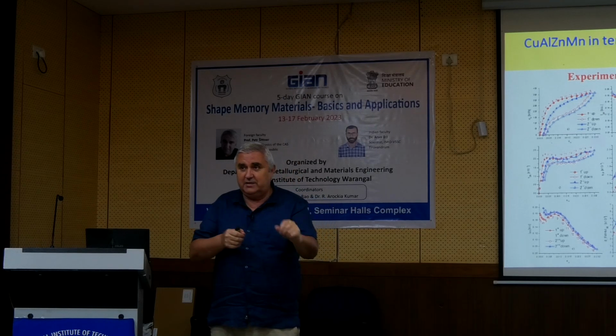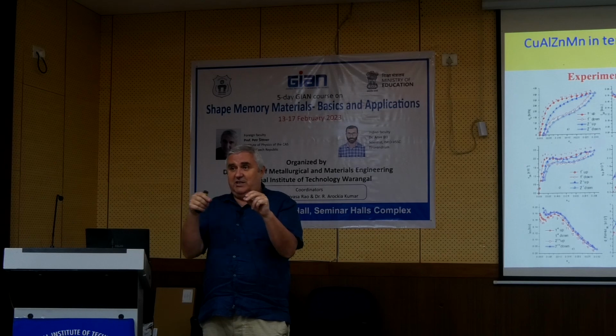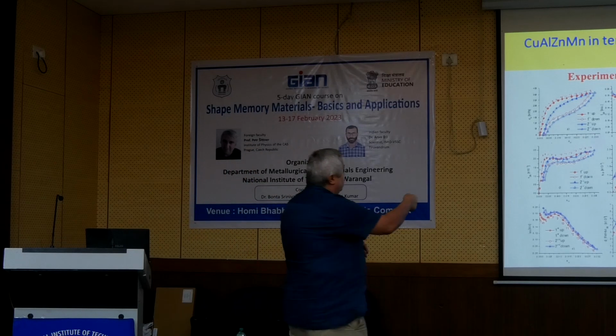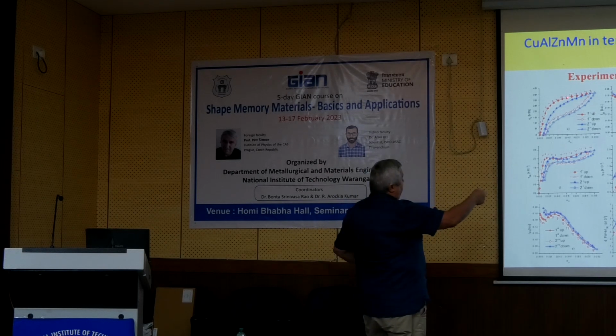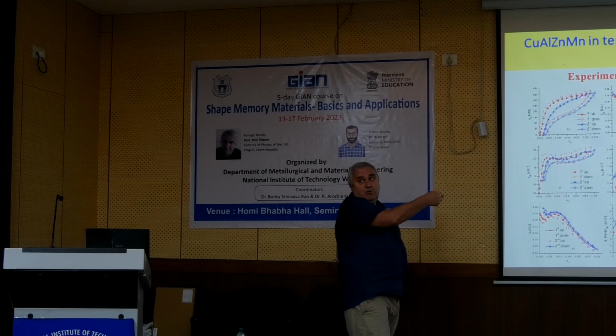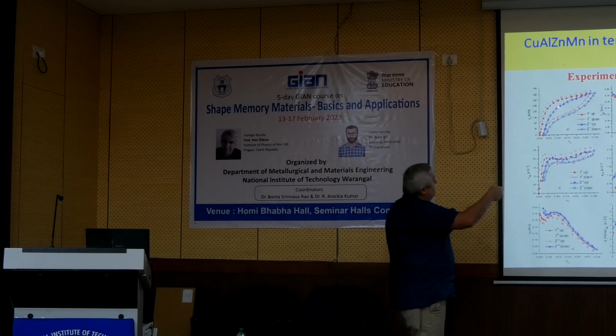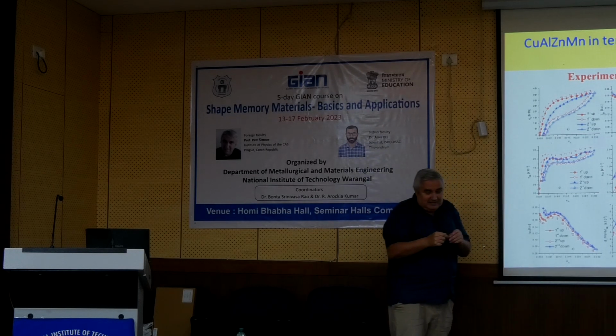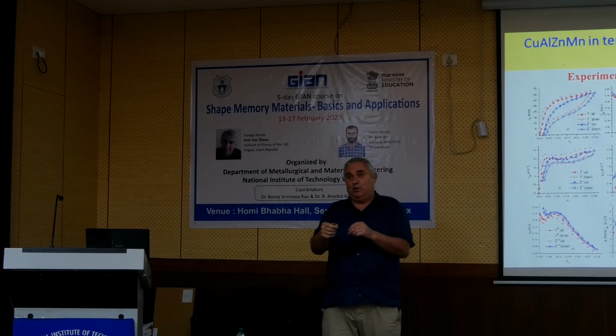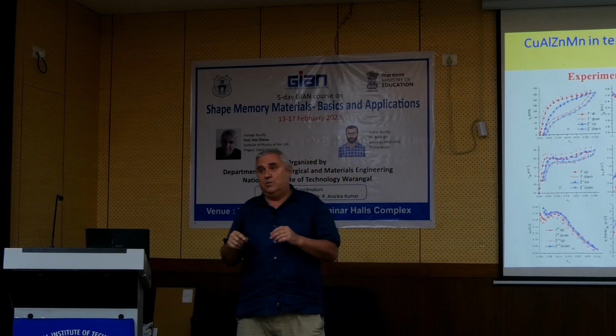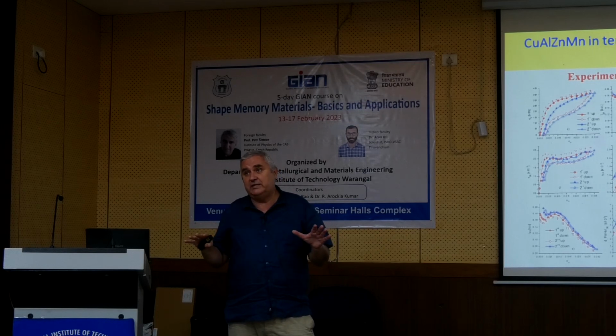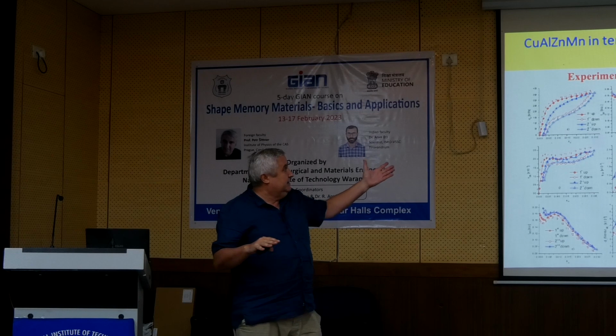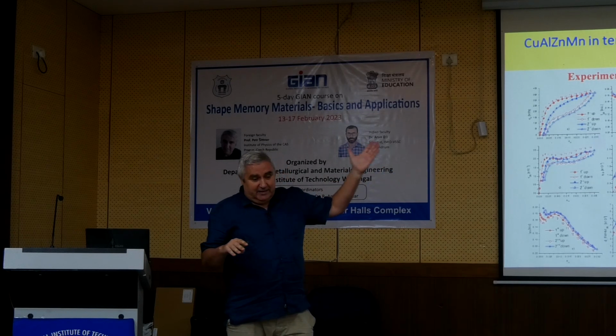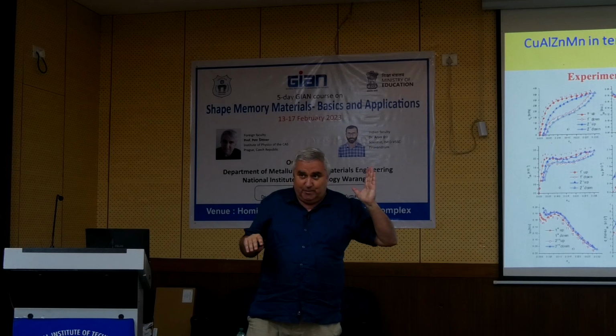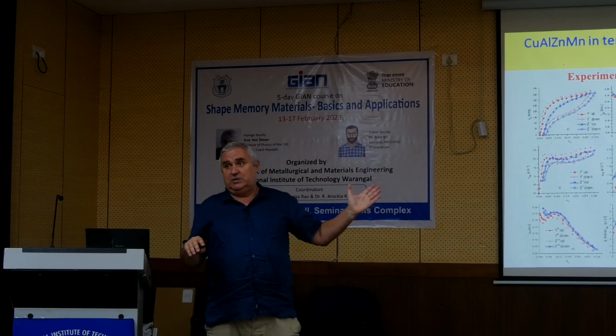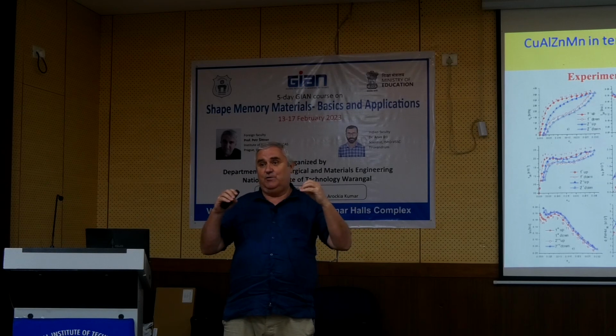And then if you are loading, this internal stress sums with the external stress which you apply. And because of that, typically in the second load, you will have a lower stress. Why do you have lower stress? Because if you load for the second time, the internal stress helps the transformation to proceed, which is already inside your material. So if there is no plasticity, there should be no internal stress. But in case of copper aluminum nickel polycrystal, it will break because there is no slip, and the sample will break and you will have fracture.